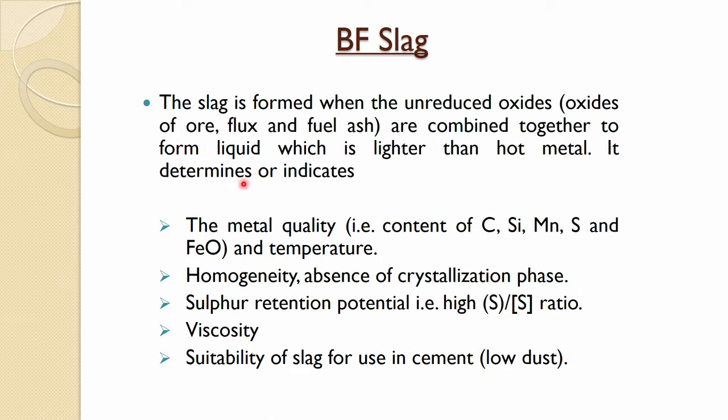So, it determines or indicates the metal quality: content of carbon, silicon, manganese, sulfur and FeO, and temperature. So, from the slag composition, one can know what would be the metal quality and temperature. Homogeneity, so absence of crystallization phase like titanium carbide and those.